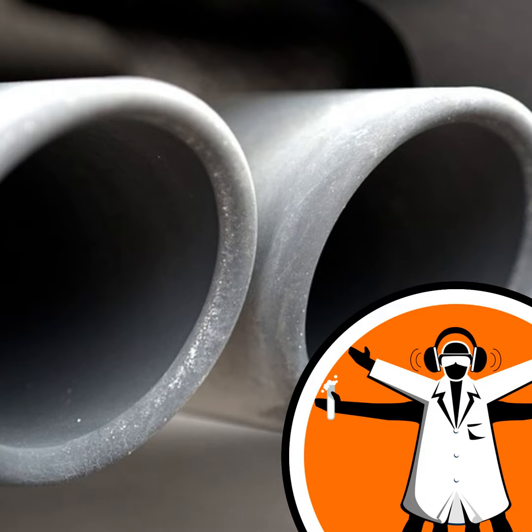They found their catalysts were stable and could do numerous cycles without deteriorating, but they've only really tested on the matter of days when you want a catalytic converter to work for a year or more to be practical. And there are other things we want catalytic converters to do. So nitrogen oxides, NOx, in car exhaust also needs to be treated as well. It may be possible to combine the researchers' new catalyst and put some extra ingredients onto it that will try to do everything all in one stage. Or it could be part of a separate system where you have effectively 2 or 3 catalytic converters in series with each other in a row.